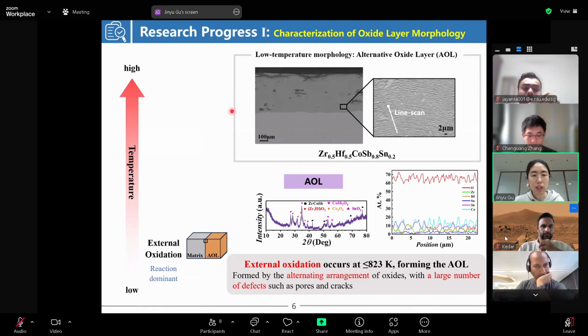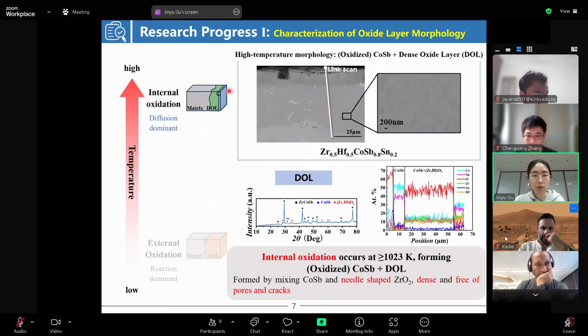It was found that in the low temperature region, the material undergoes external oxidation, generating the AOL, formed by alternating arrangement of oxides with a large number of defects, such as pores and cracks. And in the high temperature zone, the material undergoes internal oxidation, generating a cobalt antimony layer and the DOL, a dense oxide layer formed by mixing cobalt antimony and needle-shaped zirconia.